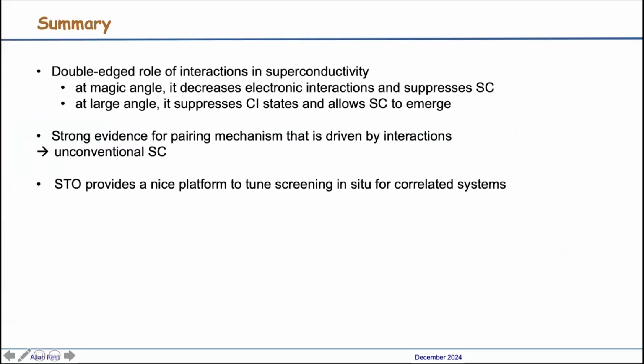Okay. So in summary, it looks like the interactions play a double-edged role in superconductivity. At magic angle, screening decreases interactions and suppresses superconductivity. At a large angle, it suppresses the insulating state and allows superconductivity to emerge. So there could be, I would say, maybe a pairing mechanism driven by interactions. So maybe it's pointing towards unconventional superconductivity. But I want to say that STO is now a very nice platform to tune screening in situ for correlated systems, for example, other correlated systems like moiré TMDs or rhombohedral layer graphene.